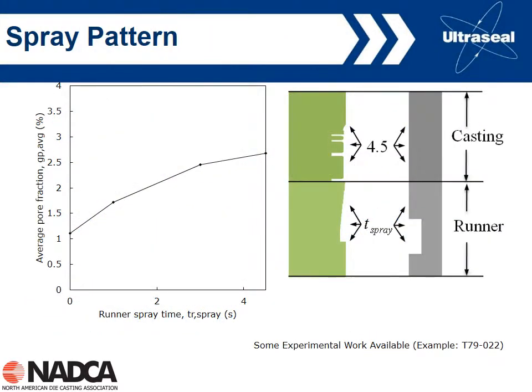And so again, we can look at the effect of spray, and here we're looking at the effect on directional solidification. Again, this is a simulation where we're spraying the top of the casting, and we're looking at the effect of changing the spray time on the gate. And so, on the runner I should say, as we increase the spray time, we can actually increase our pore fraction. What's happening is that we're cooling the gate too much at the surface. It's solidifying very, very quickly. Therefore, we're less able to feed shrinkage, and therefore we're actually increasing our pore fraction.